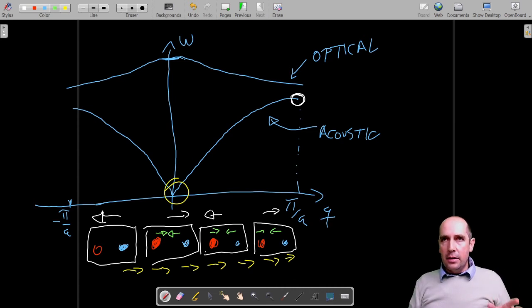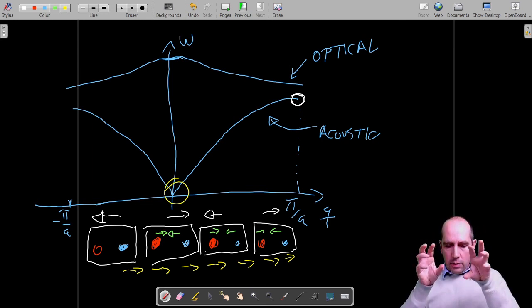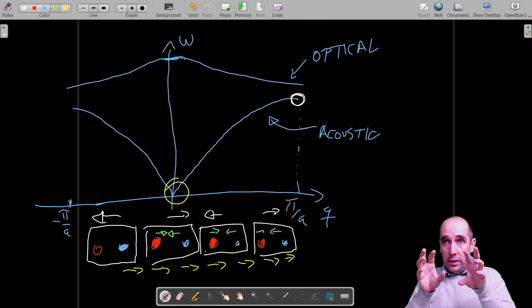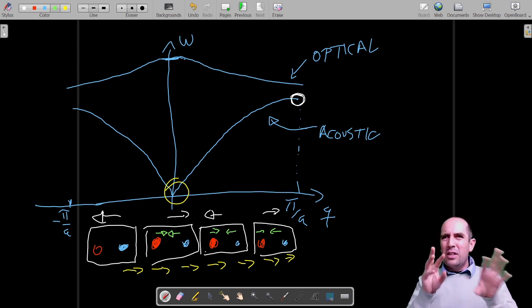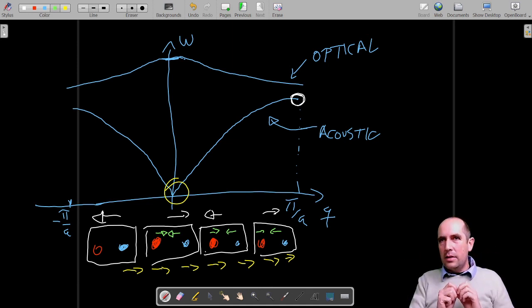can be excited by optical means, and this is a little bit harder to understand sometimes, but if you think of these two types of atoms as really two atoms that are different, and being different, there could be a dipolar moment between them, which if we have just identical atoms is not possible.